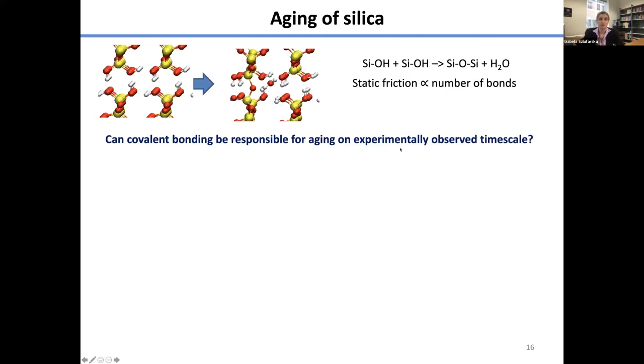So we did that. We have performed such simulations for, again, silica-silica. Part of this because there were experiments available, part of this because our funding was coming from geology. So we have considered the energies to form these kinds of interfacial bonds. We put it into our KMC model, and we asked whether these covalent bonds can lead to experimentally observable aging. So when you put surfaces together, do the bonds form spontaneously, instantaneously, and the interface is bonded, or do they form over long enough time to be able to see this kind of evolution experimentally?